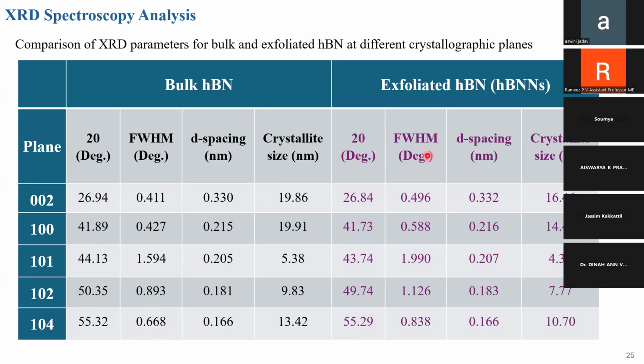And here comes our next parameter. Full width half maximum, you can see that it has changed. Yes, while exfoliating, it is increased. You can check each plane. In every Miller index, or every atomic plane, this FWHM is increased, and the d-spacing is also increased. And as you are exfoliating it, the crystallite size should be minimized.